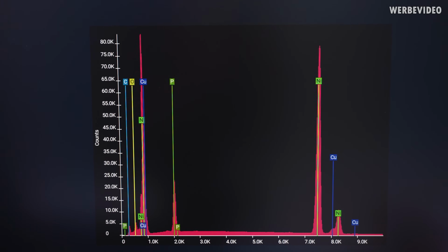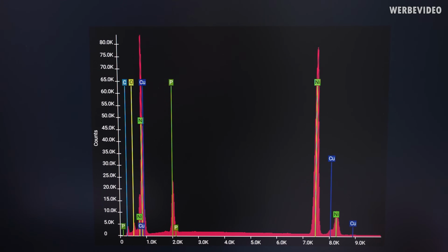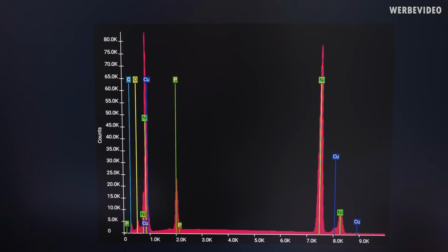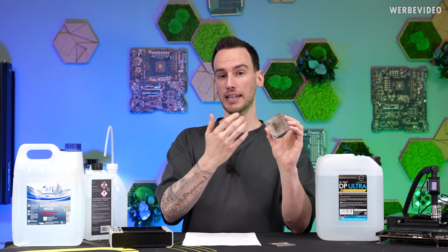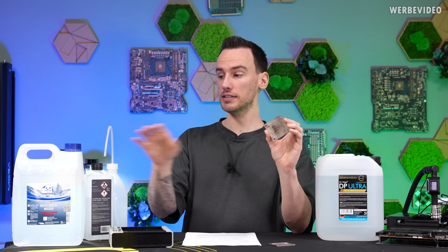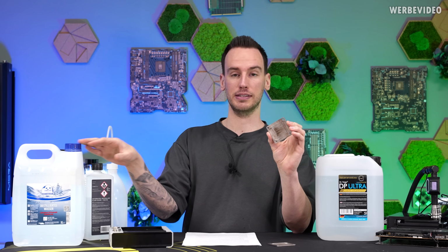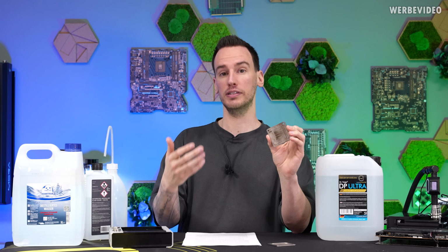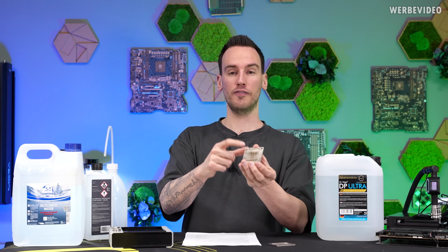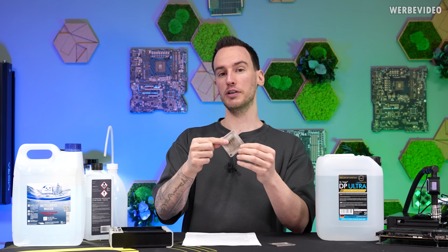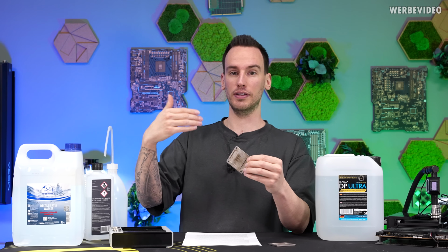And then I did a comparison and compared an area where we didn't see visual corrosion, and it looked exactly the same. So what happened in exactly this case is that the distilled water was taking up some of the copper ions, so the Cu2+ ions, from the part itself, and it was basically deposited on the nickel itself.